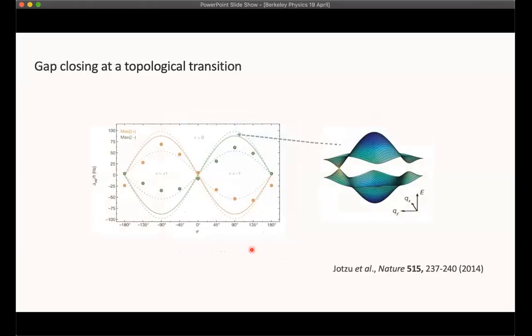Now, there are previous examples of using the closing of a gap to identify topological phase transitions. This is an example from a group in ETH Zurich who built a honeycomb lattice for ultra-cold fermions. And they, in varying the potentials at the different lattice sites and applying modulations to those traps, were able to realize the topological Haldane model. So the Haldane model is characterized by a topological phase transition between regions where the Chern number is 0, so that's sort of outside of this shape, and where it's plus or minus 1. And that phase transition occurs at a point where, or actually along this whole contour, where the gapped band spectrum closes at a single Dirac point. So the gap closes right here, for example, at this point.